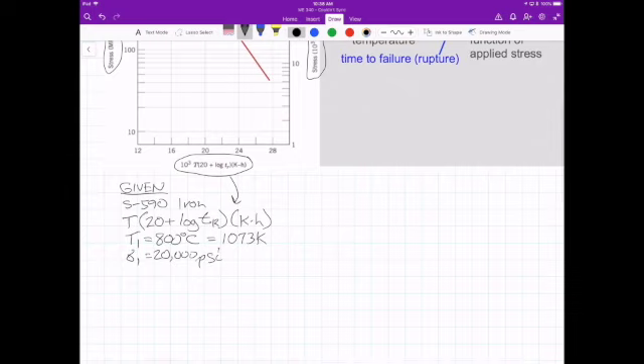Okay, I'm also going to add a second temperature. What if we change the temperature, drop it 50 degrees C, which is pretty minimal temperature drop for a metal? This would be equivalent to 1023 Kelvin. Okay, so as we should be able to predict, higher temperatures exponentially increase strain, which would decrease the time to rupture. So a small drop should exponentially increase the time to rupture. So let's do that calculation and see what we get.